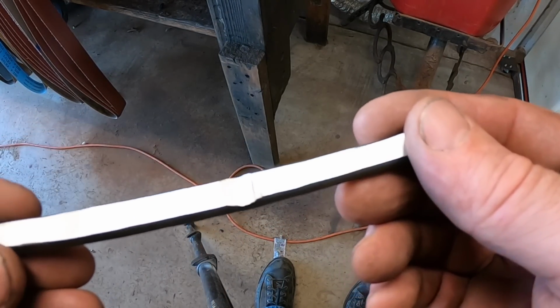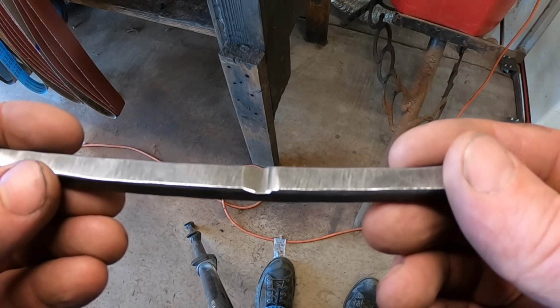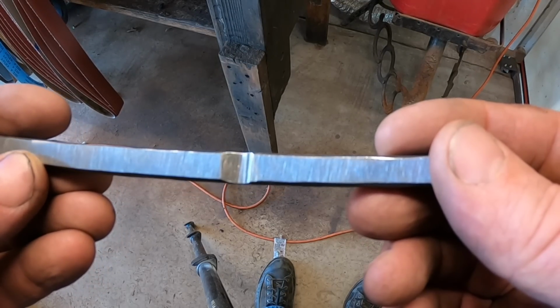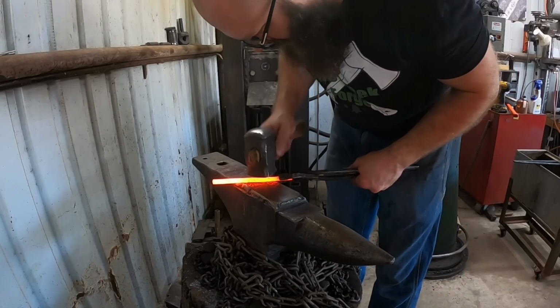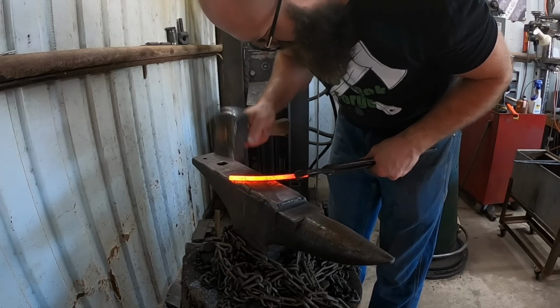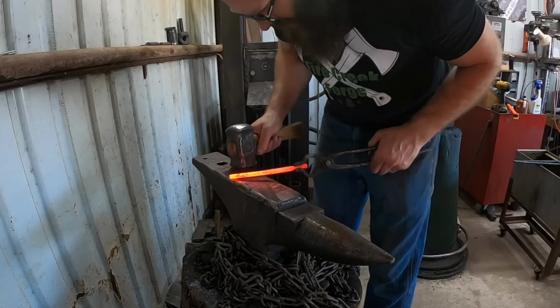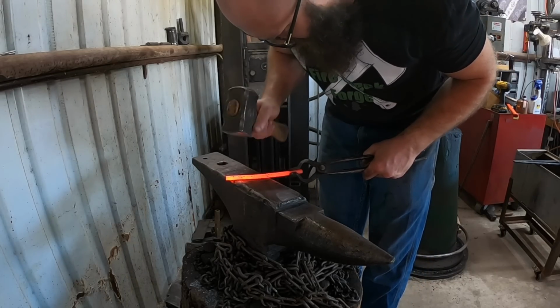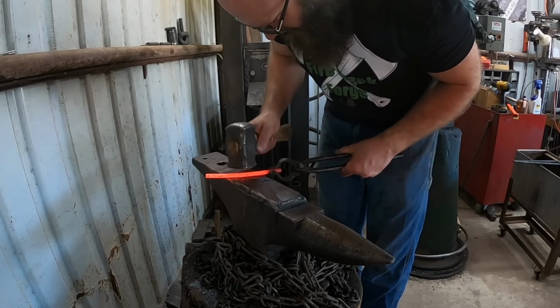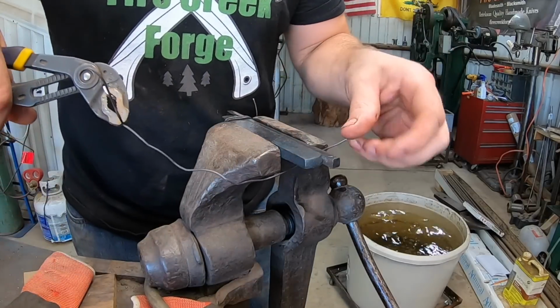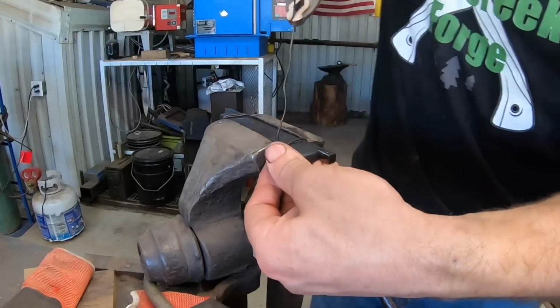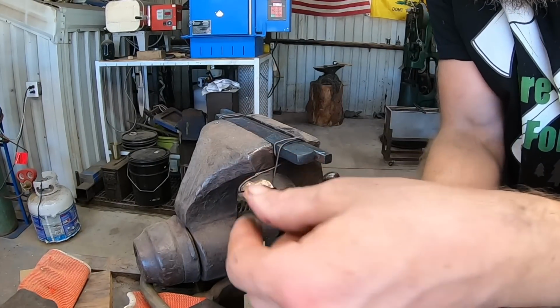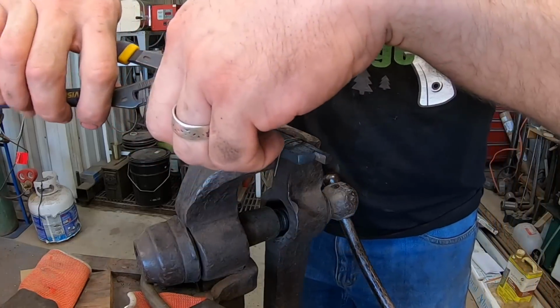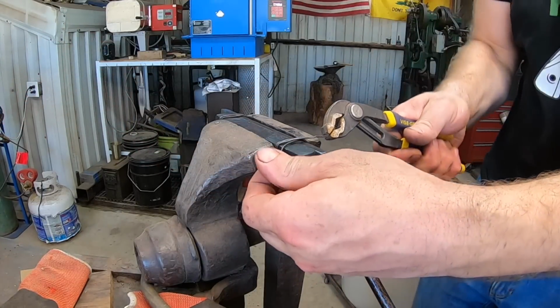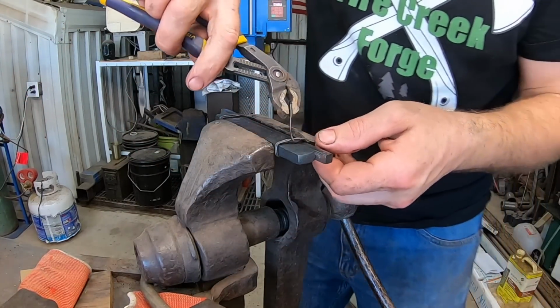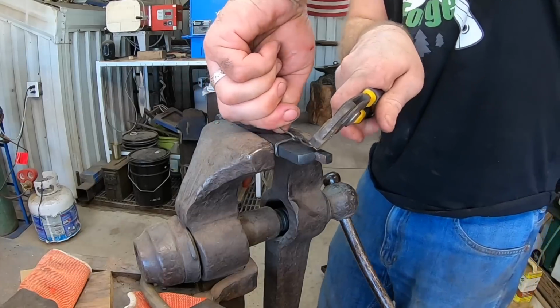O1 tool steel is a deep hardening steel. It's a lot more prone to cracking if you forge it at low heats, and/or if you quench it in water. Even if it's not at a high heat, if it's still cooling down, it can stress crack it. I don't know if you were able to see that on the camera, but there was a line there in the steel, an internal crack. Can't have that in the blade, so I went ahead and made up another piece for this.